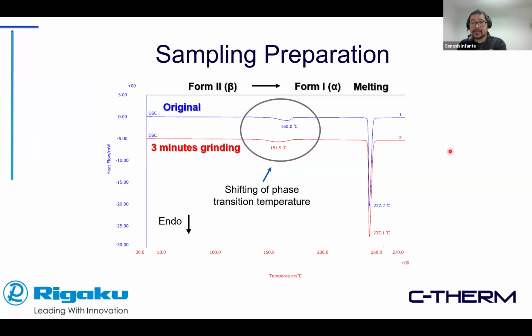And speaking of sample prep, sometimes if you're dealing with something like, if you want to powderize something, you want to grind it down. So for something like a polymer application, that can be an important factor, especially if you're considering recycling and looking into what kind of polymers are available in that particular mix. And you can see here that without any type of grinding and conditioning, there is this profile, in this case for crystalline caffeine. But after grinding that crystal and retesting it, you can see that there is a shift right here where now it's at a significantly lower temperature. However, the melting profile is still pretty much identical to each other. So it's just something to keep in mind, that sample prep can somehow introduce bias into your measurements.